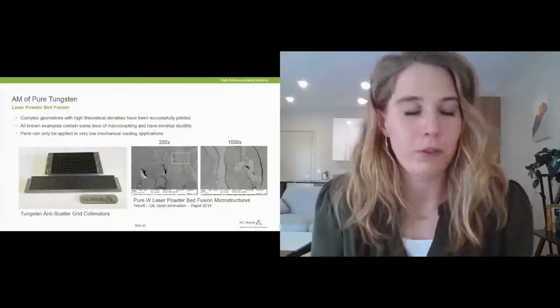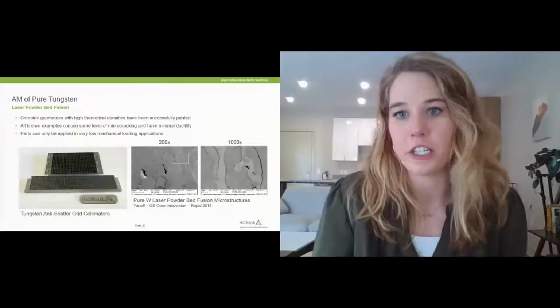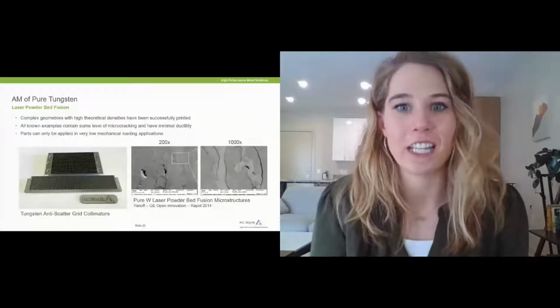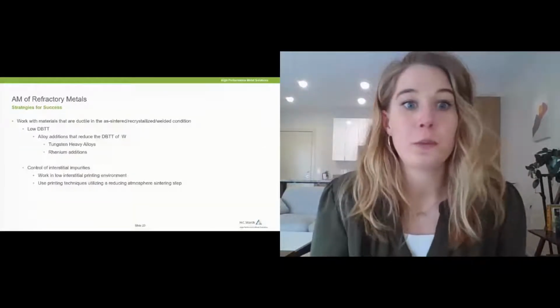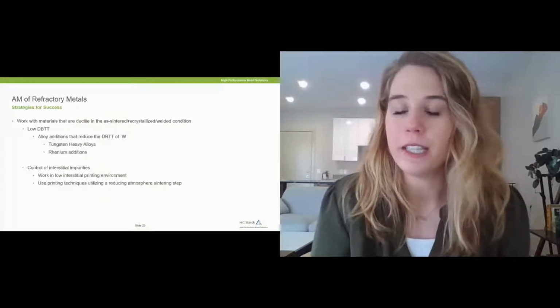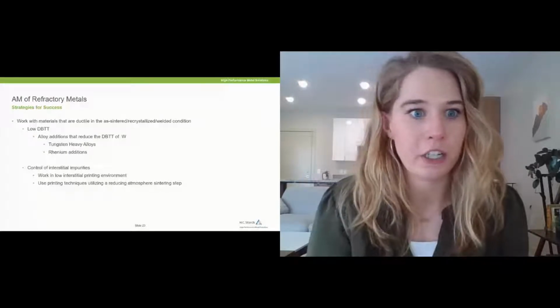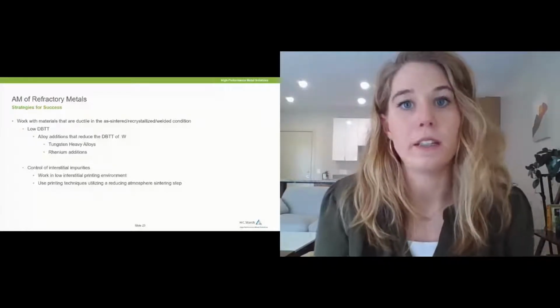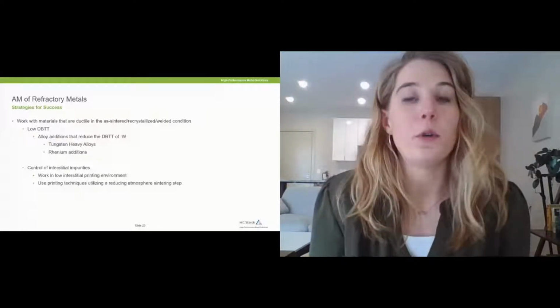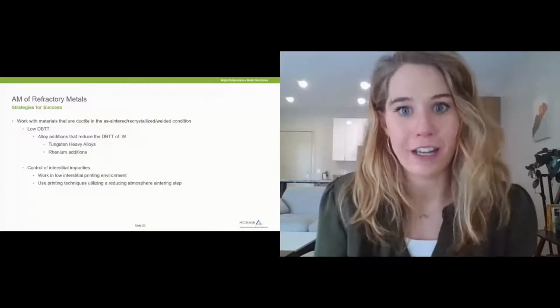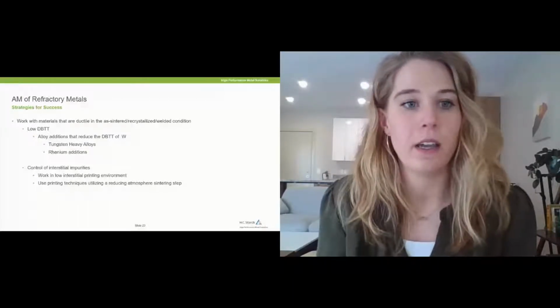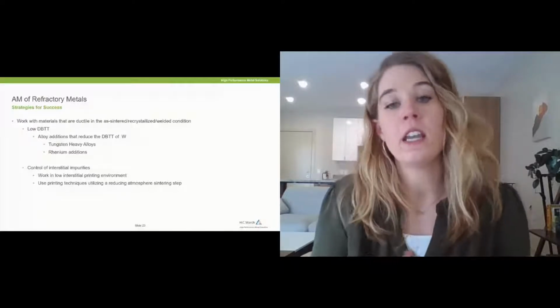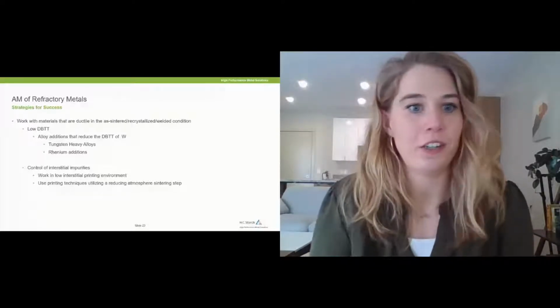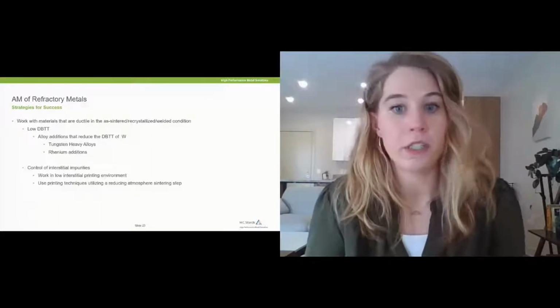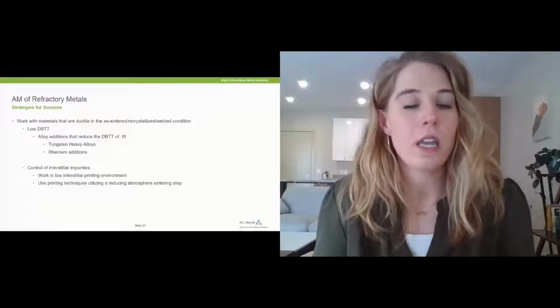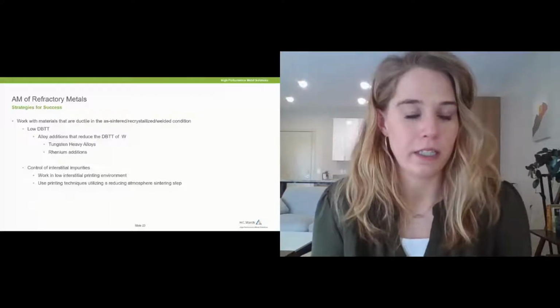So at H.C. Starck, we looked at what other strategies we have to make tungsten successful for additive manufacturing. So since we know that we need to work with materials that are ductile in the as-sintered or welded condition, we need to figure out another way to lower that ductile-to-brittle transition temperature. So one strategy to do so is alloy additions. Specifically talking about tungsten, tungsten heavy alloy is a good alternative. So again, tungsten heavy is the tungsten with the addition of nickel or iron. Also rhenium, which is another refractory metal but is very ductile, can be added as well to increase that ductility.